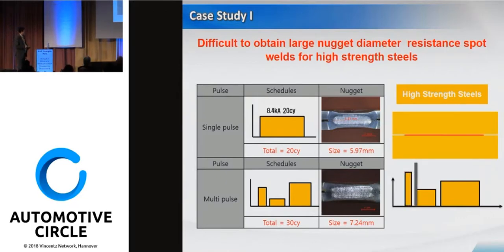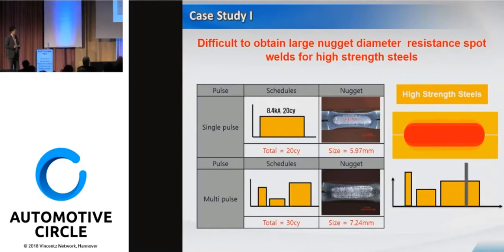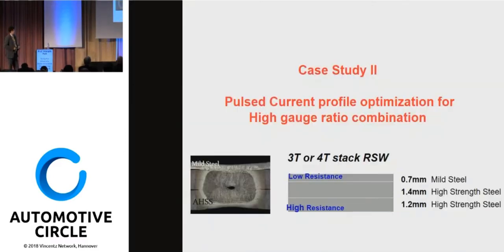You have a large contact area. In intermediate welding, you stabilize this contact area. Now in the main pulse, you can grow the actual nugget very quickly. So this is how we get the 7.24 millimeter nugget diameter for, I think, 1.2 gigapascal high strength steels. So here's another case study too.